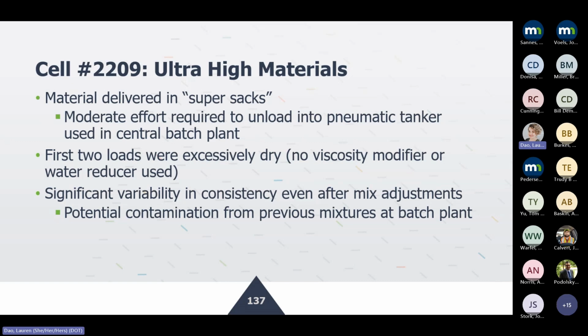And the first 2 loads, like I mentioned, were excessively dry. I will show you a couple of video clips if they play. But then the batch plant realized that they forgot to add the viscosity modifying admixture and the water reducer. And then we had to wait 45 minutes for the next batch, which came out slightly better. And then I think the third batch was much better.